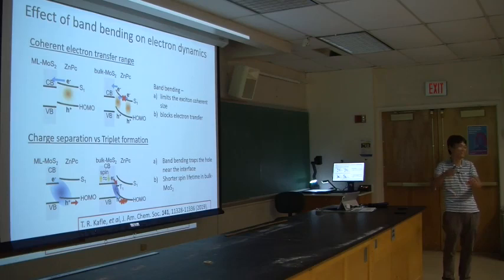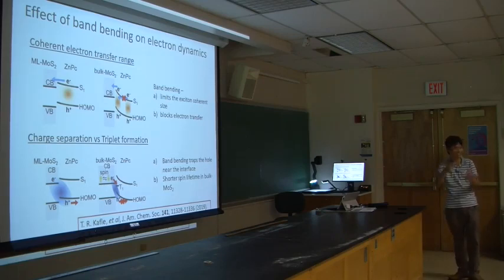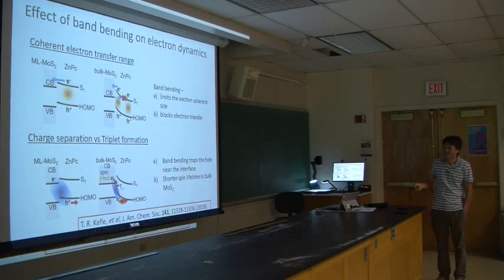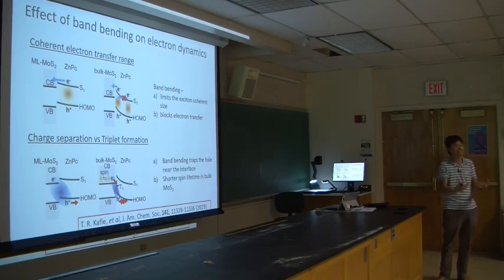So you have a hole there, which means that instead of two electrons, you have one electron and one hole, right? So that electron and the excited electron, if they have the same spin, you have a much lower energy versus if they have opposite spin, right? Singlet and triplet. Because of that, if you have spin flipping, then these electrons can go back to form this lower energy exciton, which is actually what happened. Then you form this triplet state.